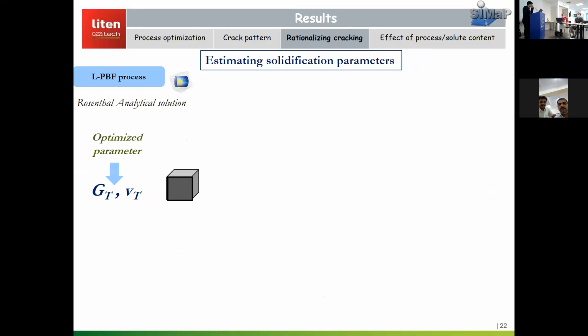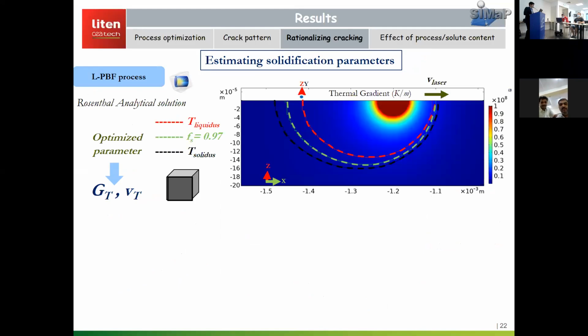Now, another part of the puzzle is identifying the solidification parameters. We chose the optimized parameters and used the Rosenthal analytical solution to get an idea of thermal gradients and solidification velocities. Here is the building direction thermal gradient map, where the laser is moving along the x-axis on the right side, and using the Rosenthal model, we can identify the thermal gradients. There are different curves: the red contour indicates the liquidus temperature, the green contour indicates the coalescence temperature at a solid fraction of 0.97, and the black contour indicates the solidus temperature.